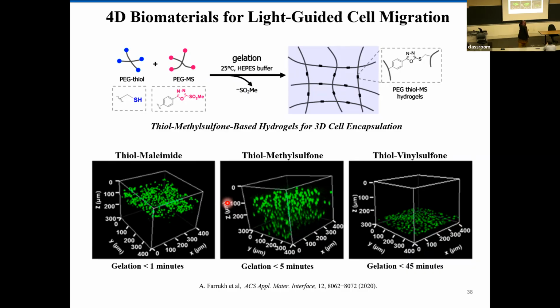So then we try to use our 3D thiol-methylsulfone chemistry here, not only for binding the molecule, but actually as a cross-linking chemistry. With this thiol-methylsulfone chemistry, in this case, the gelation happens between 3 to 5 minutes, which means that when you are trying to mix everything, you have enough time to mix everything. And then this gel starts to gelate, and cells are really distributed within the system. So with this system, we see that your surface functionalization and the chemistry that you use to functionalize your surface is extremely important. If we can control that, we have a lot of control, not just over the stiffness, we have control over binding, we have control over degree of polymerization. Just by choosing the right chemistry, we can have multiple controls over our artificial material that we are trying to create.